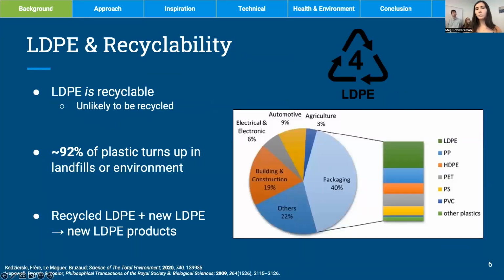Okay, so it's important to note that LDPE is recyclable. However, a 2020 study found that plastic manufactured since the 50s has mostly not been recycled. So less than 2% has been recycled, and less than 6% has been incinerated, and approximately 92% has turned up in landfills or in the environment. And because most plastic doesn't get recycled or recycled properly, it's really important to pivot to a more biocompatible alternative going forward.